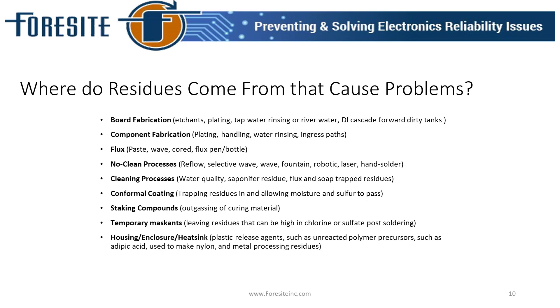Staking compounds, outgassing issues, temporary masking, and the hardware enclosures themselves — plastics, vibration-dampening foams — all have a tendency to outgas sulfur, chlorine, and acetate, which also set up corrosion cells. Understanding what those elements are allows us to use a localized extraction, see the corrosion site, and say: this residue came from this step in the process. We go back to that process or material, make the change, remove it, bring in new materials or processes that are cleaner. That's how we've been successful for the last 29 years.